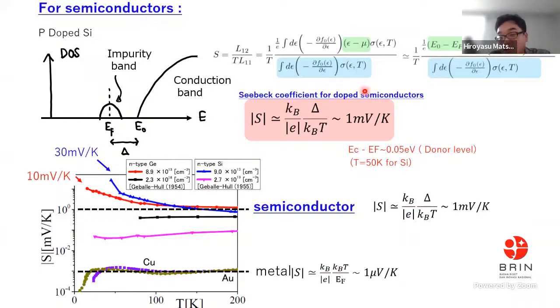So next I talk about the semiconductor case. Using these equations, we can get the Seebeck. Yesterday I already showed this equation. So in the semiconductor case, Seebeck is expressed by this equation, and the amplitude is around 1 millivolt per Kelvin at, for example, 50 kelvins, in the phosphorus-doped silicon case, around here.